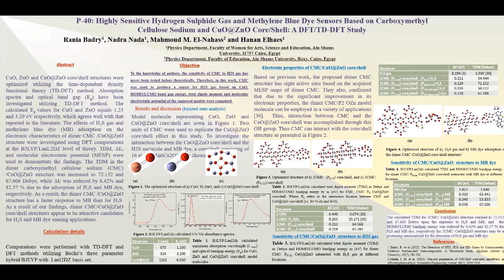The sensitivity of the CMC, copper oxide, zinc oxide core shell structure to H2S gas and to methylene blue dye. As we can see from Figure 4, there are different positions for the interaction of the H2S gas and methylene blue dye with the CMC, copper oxide, zinc oxide core shell structure.